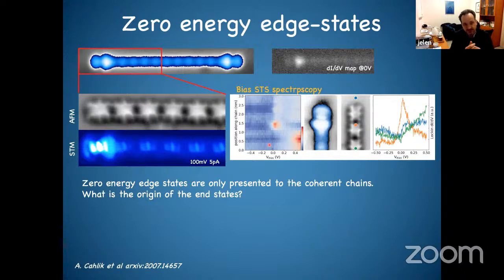But there is one more thing. When we look at these straight chains, there is the appearance of edge states, or band gap states inside. What you see is a very strong peak at zero bias, or very close to zero. At first we thought that maybe it's also related somehow to topology. Unfortunately, we calculated the Zak phase for this, and we found that this should not be related to topology. So how to explain the origin of this edge state here?